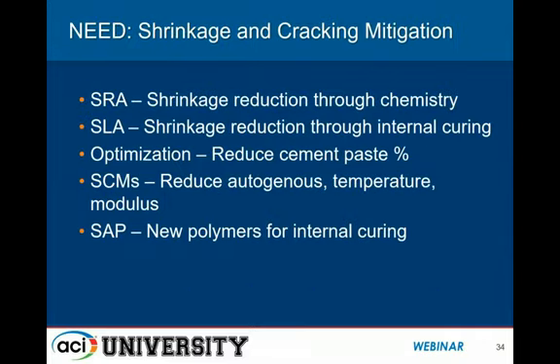How do we expect the industry to respond to this spec and meet these requirements? Well, I think that shrinkage mitigation is the key, and really a lot of different strategies will work, but the top strategies that I have seen utilized are the shrinkage reducing admixtures and the saturated pre-wetted lightweight aggregate. In addition to that, we're seeing a lot of producers now veering towards optimization of their aggregates and incorporating a mid-size coarse aggregate to try to minimize void space, and utilizing higher percentages of SCM, which we've also seen provide a lot of positive benefit in reducing autogenous shrinkage and helping with the cracking issue.